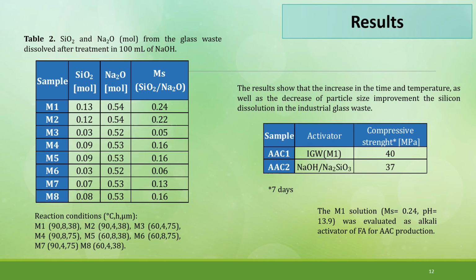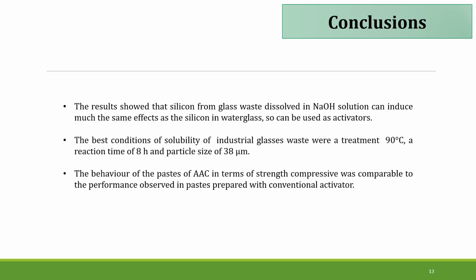Finally, with the activator with the highest ratio, an alkali-activated cement was manufactured and its mechanical resistance to compression was measured after 7 days of curing. This was compared with another alkali-activated cement manufactured from a mixture of hydroxide and silicate, and it was observed that materials with very similar strengths are obtained, the cement created from the alternative solution being slightly higher. The results showed that silicon from glass waste dissolved in sodium hydroxide solution can induce the same effects as the silicon in water glass, so it can be used as an activator.